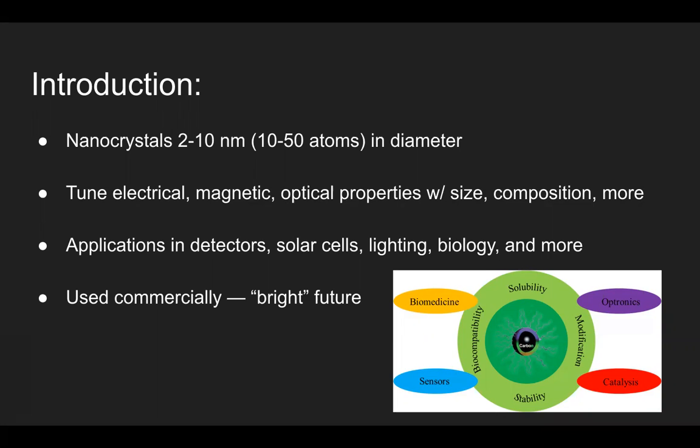Quantum dots provide great flexibility and versatility for a variety of devices and applications. The most important and relevant property to manipulate is size. Quantum dots have a band gap just like bulk semiconductors, but unlike bulk semiconductors, this band gap is incredibly sensitive to the dimensions. By reducing the size of a quantum dot, you can increase its band gap, and by increasing it, you can decrease this band gap.